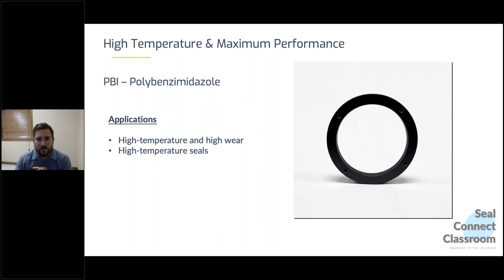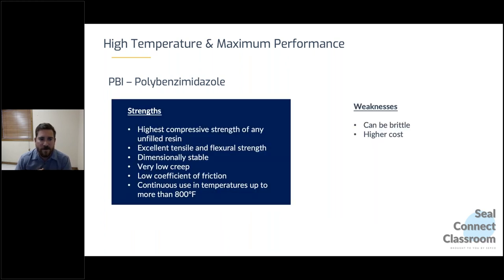Some quick applications for PBI, getting high temp, high wear, bushings and seals and such. Strengths of PBI, it's the highest compressive strength of any unfilled resin. So this is the strongest material of anything that's out there right now. Excellent tensile strength, excellent flex strength. It's very dimensionally stable, almost no creep, low coefficient of friction, and it can be continuously used, really 800. We're being conservative with our numbers, but it is a very high temp material. It can be a little bit brittle, and it's more expensive. It's in fact quite expensive, but in these higher temperature applications, it's a fantastic material. So let's go to the next slide.